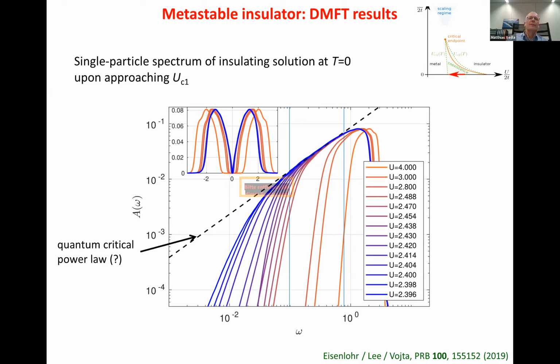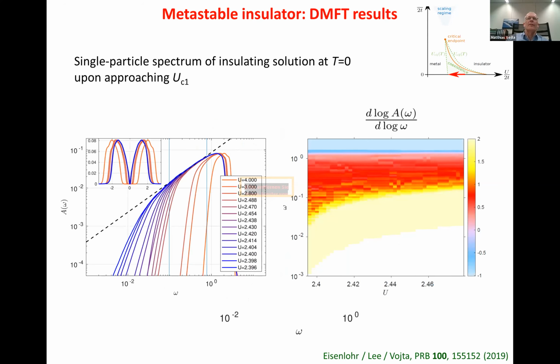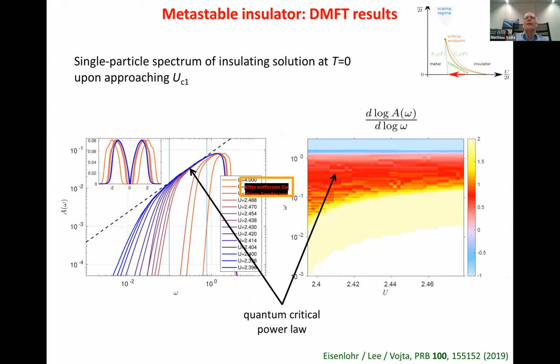But this is promising. The right-hand plot shows the effective exponent of this spectral function, color-coded, as a function of U and frequency on the vertical axis. Red means we essentially have this power law, with an exponent around 0.8, meaning there's a sizable range of U and frequency values where this power law seems to be realized.